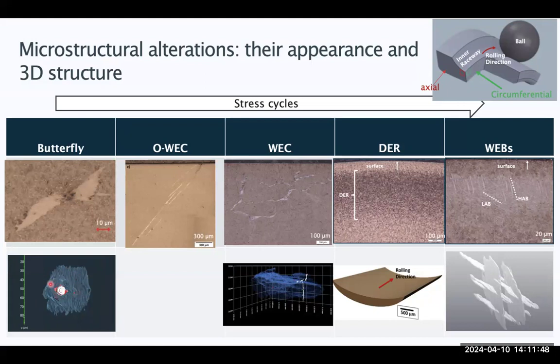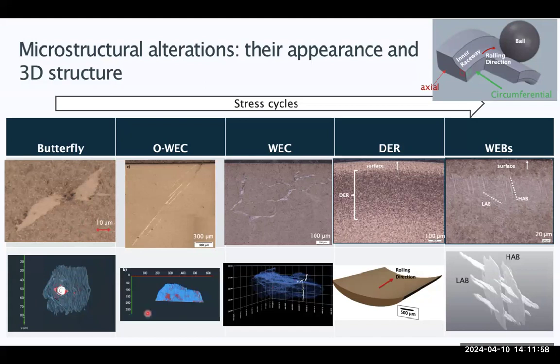Just to clarify, the gray is the white area, the white is the inclusion, and the red are the cracks and the voids. We also looked at the orientated white-etching cracks. These white-etching cracks are much, much bigger than butterflies, probably over 100 micrometers in length. This is only part of one of the orientated white-etching cracks we were able to analyze.